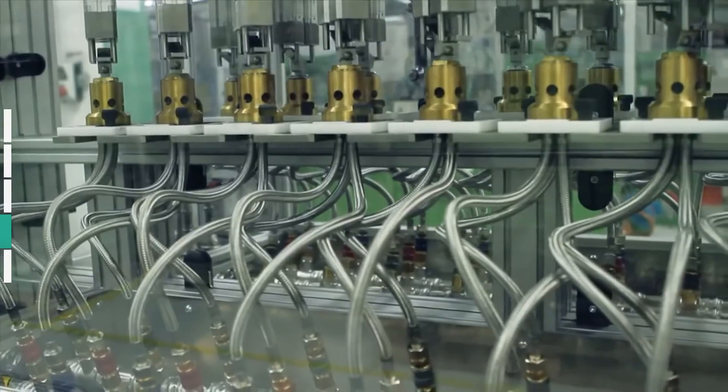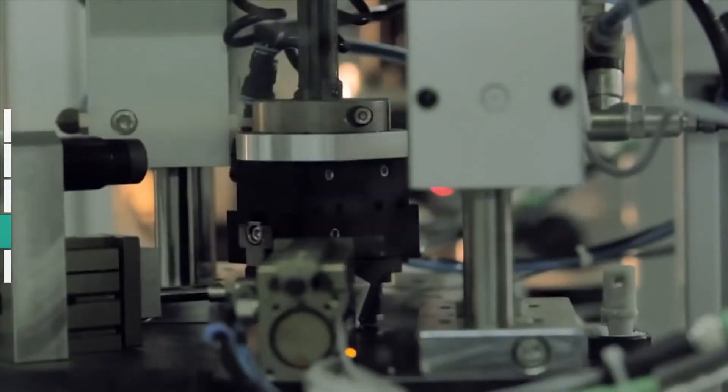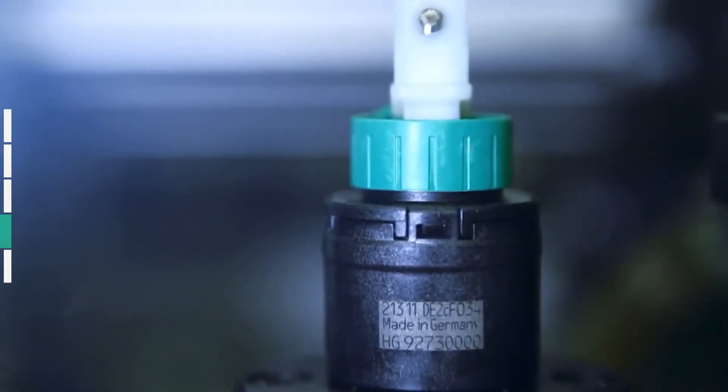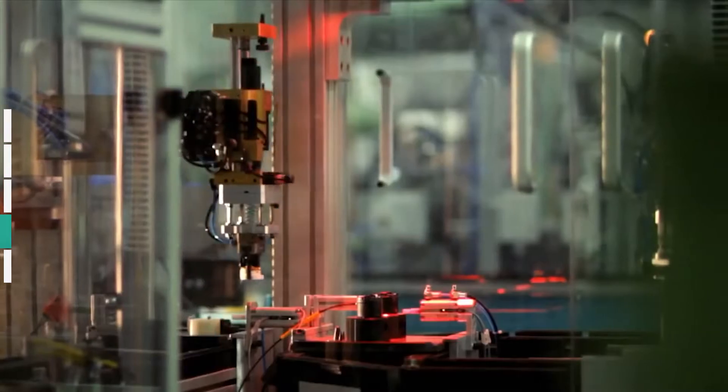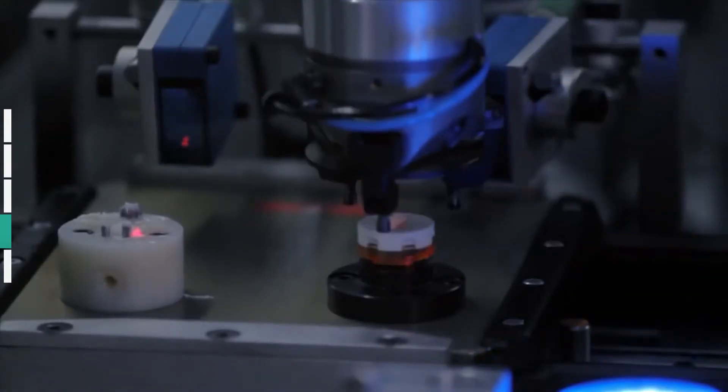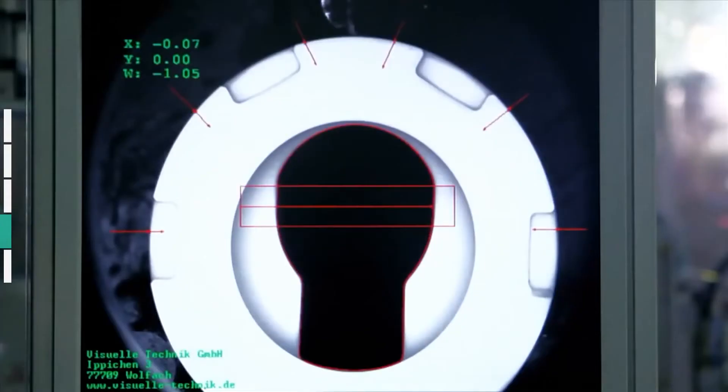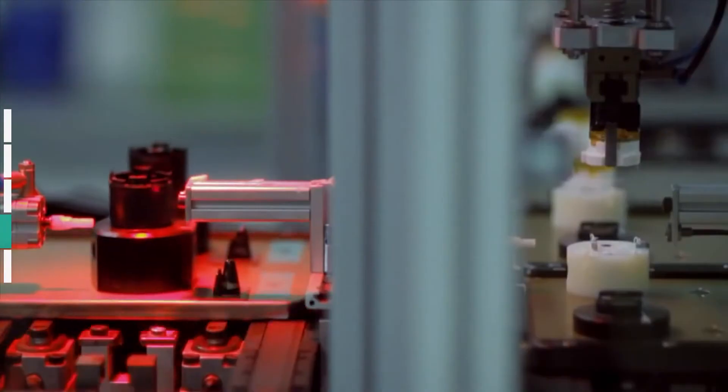The stress test highlights what the cartridge has to do every day. Its work in the home is tested and simulated around 70,000 times. What are the key quality criteria? The motor has to run smoothly, as people want to conveniently mix their water in the bathroom and kitchen. So everything depends on the perfect torque. To this end, the ceramic discs are precisely cut to six thousandths of a millimeter and coated with a thin silicone film, making them robust, smooth and mobile.